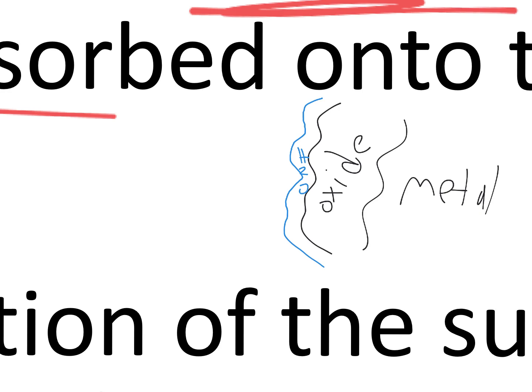What we can do is work with these carboxylate structures. And those of you who haven't seen this before, this is a carbon double bonded to an oxygen, and then there's a hydroxyl group bonded to the carbon as well. And then there's stuff out here, which we'll talk about in a second. Four bonds to carbon. But these guys, they like water, all right? OH and water, they're good because they're like each other, all right? And so there's an attraction going on between these species and the water surface. These are polar bonds with a polar liquid. They can get together and form hydrogen bonds, right? One of the strongest van der Waals bonds known to man are hydrogen bonds. And so this will draw in this carboxylate to the surface and bind it there.